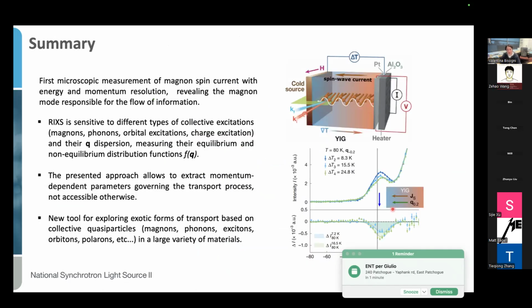So in conclusion, I hope I convinced you that we performed the first microscopic investigation of magnon spin current with energy and momentum resolution, and we revealed the magnon mode that is behind this magnon transport process. For doing that, we have used RIXS, a technique sensitive to different types of collective excitations like magnons, but also phonons, orbital excitations, charge excitations, and their momentum dispersion, and also sensitive to the equilibrium and non-equilibrium distribution functions. The approach presented, based on RIXS, can extract momentum-dependent microscopic parameters that would not be accessible otherwise.